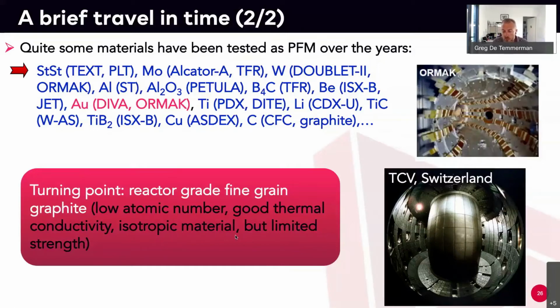Carbon or graphite sublimates. So if there is too much heat, you create a carbon vapor, but you don't go into a liquid phase. That's very important because it means your material is extremely resistant to heat. Yes, you can have a big vaporization of carbon, but it maintains its shape. As soon as people switched from tungsten to carbon, the performance of devices doubled, they reached much higher temperatures, and fusion made a lot of progress. You can see here a tokamak which was built in the 90s, which is fully armored with graphite tiles.